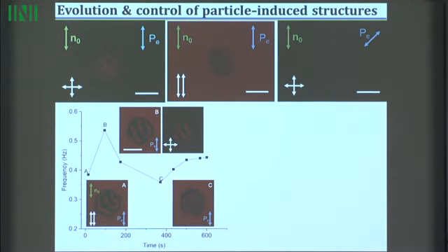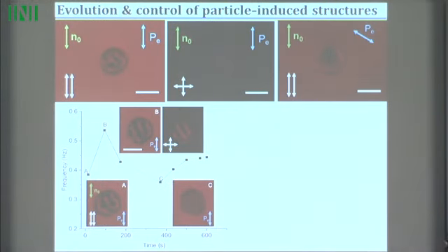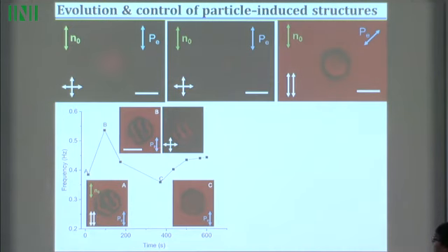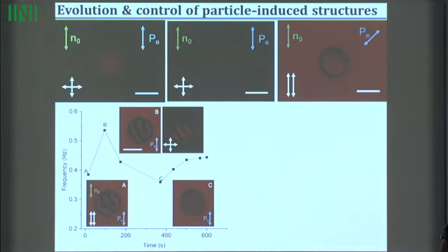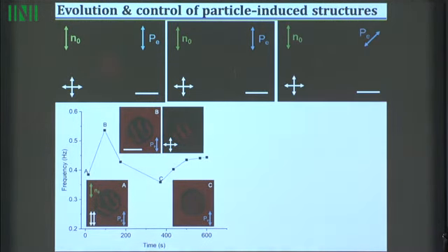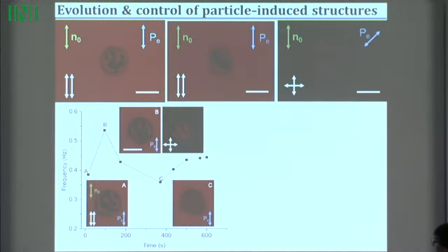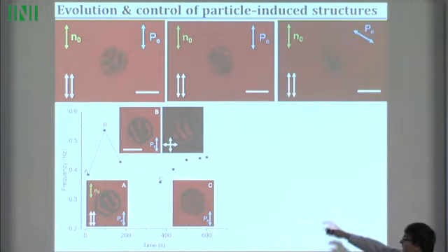So in the beginning, as you just start spinning, you oftentimes have these multiple domains because the little azobenzene molecules have tilted in different directions, a little bit to different directions, but with time these domains coarsen, and then you start getting these types of more uniform textures, as you can see in here, and that also correlates with the frequency of spinning as well.